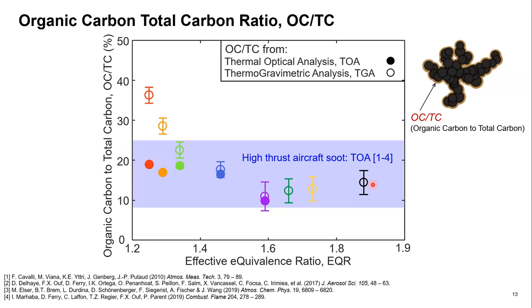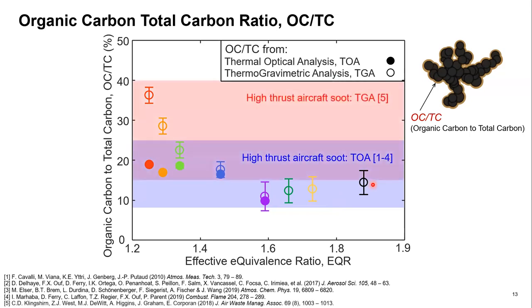And when we compare to the literature looking at high thrust aircraft soot from thermal gravimetric analysis, we see that when measuring the OC/TC ratio with thermal gravimetric analysis, we systematically see a higher OC/TC ratio, suggesting that this is a difference between the two methods. And in both cases, we are in good agreement at the lean equivalence ratios with aircraft soot, further confirming that we have produced soot similar to that of aircrafts.